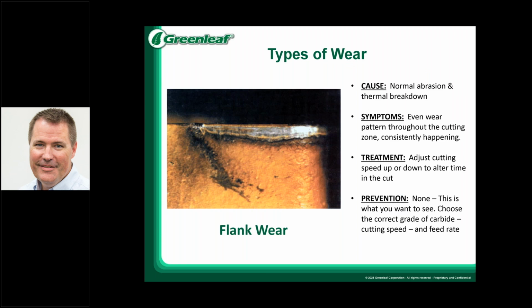First type of wear I'm going to talk about is flank wear. This is our normal wear that we like to find as much as possible. You can control this. You know how many parts you're going to achieve per edge on an insert. You have a nice even wear pattern. You can adjust with a fair amount of knowledge to be able to increase speed if you can afford to shorten the total tool life of the tool, or reduce your speed slightly in order to gain longer tool life and achieve more parts per edge.